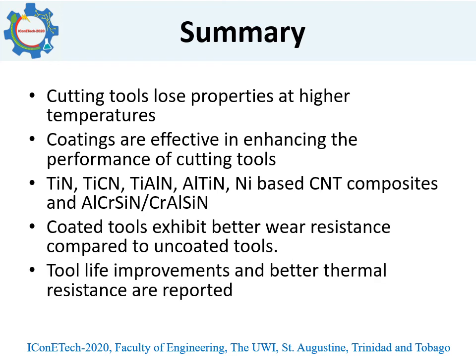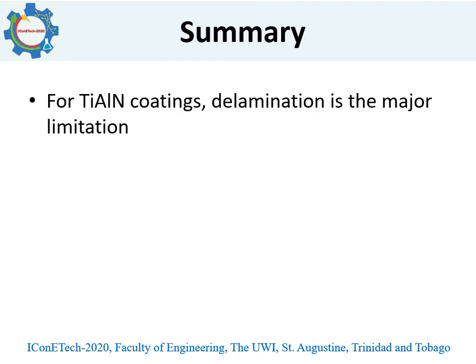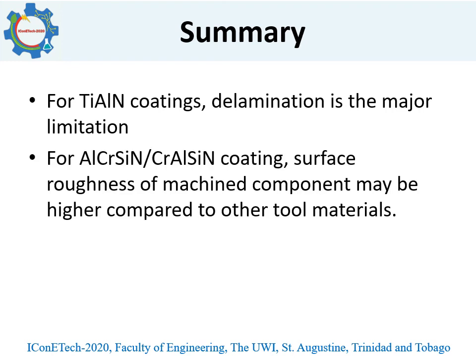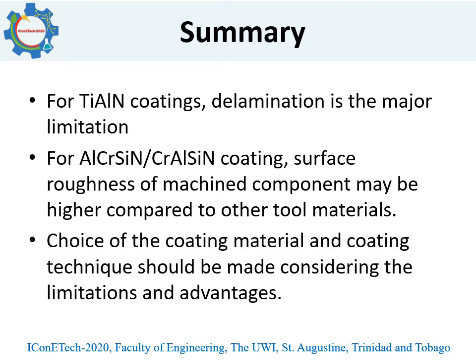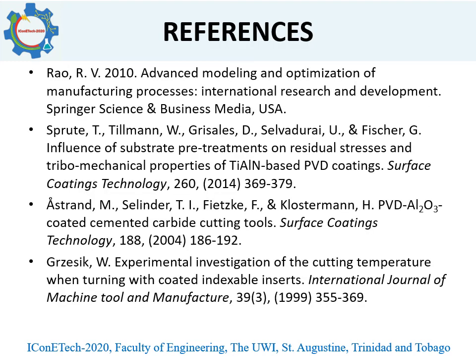Tool life improvements and better thermal resistance are reported for practically all carbide tools. For titanium aluminum nitride coatings, delamination is a major limitation. So anytime delamination becomes a problem, we need to be very careful with the choice of the substrate and the substrate's performance. So these are a few of the references.